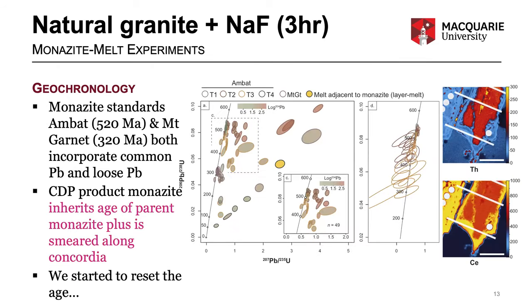In dating these 2 different grains, the 520 million year old AMBAT crystals show a range of disturbance along the Concordia and away from the Concordia. The 320 million year old Mount Garnet grains also showed lead loss trends. On the very right, you can see that the coupled dissolution precipitation process in the AMBAT crystal is driving significant chemical changes where the recrystallized or the precipitated domains in the rims have very different chemistry to the precursor crystal, even though the ages are largely inherited.